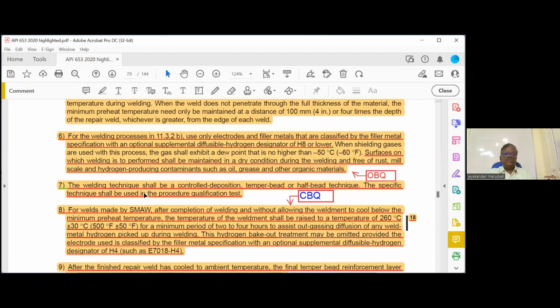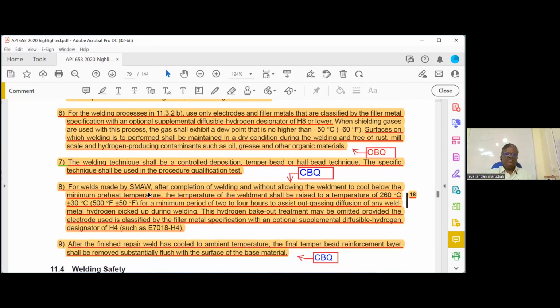Then highlight item 7. The welding technique shall be a controlled deposition, temper bead or half bead technique. The specific technique shall be used in the procedure. Either you can use temper bead or half bead. Then this is what I said. For SMAW welds, after completion of welding and without allowing the weldment to cool below the minimum temperature, the temperature of the weld shall be raised to 500 plus or minus. That is called post heating. For a minimum period of 2 hours, to assist the outgassing diffusion of weld metal hydrogen picked up during welding. This hydrogen bakeout treatment may be omitted, provided the electrode is classified H4 or lower. So with 7018 H4, no need for the post heat.